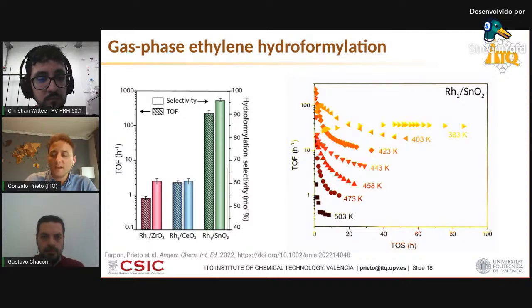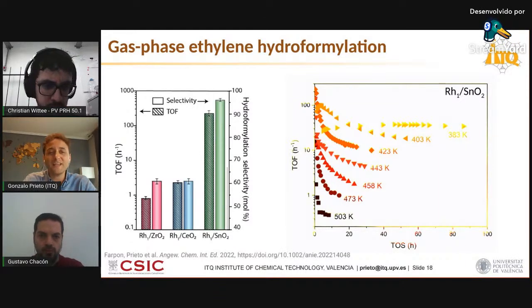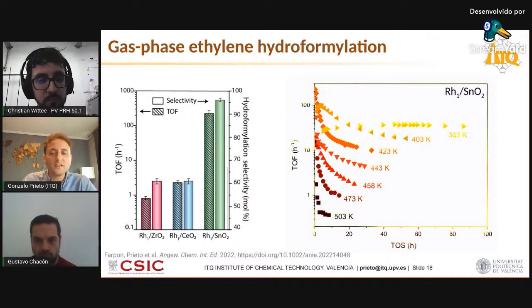No, we haven't. Sputtering deposition relies on depositing metal atoms which are already metallic in nature, and they typically don't bind very strongly to oxide supports if you do that. And friends of mine such as Gareth Parkinson at Vienna University have shown that those are more prone to aggregate at much milder reaction conditions in the presence of some reactants such as CO, even at room temperature. They skate on the surface. There are no linkages to the support. They skate and they form clusters very fast.